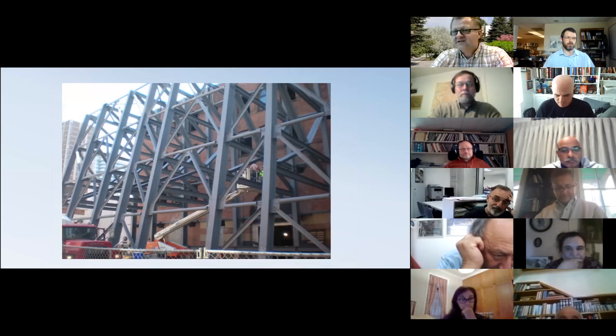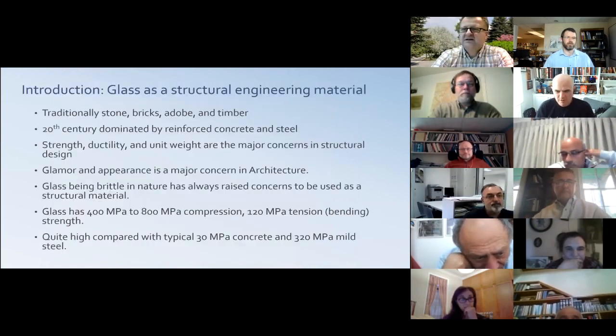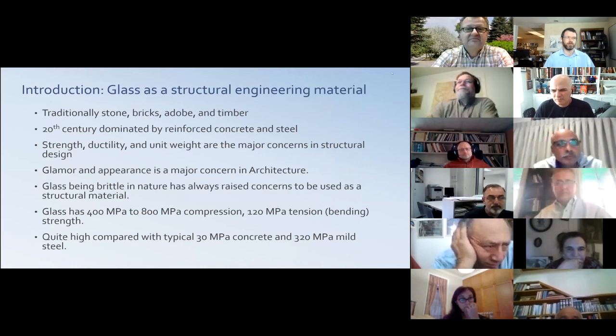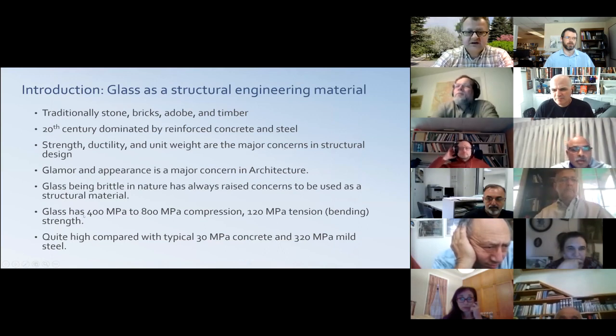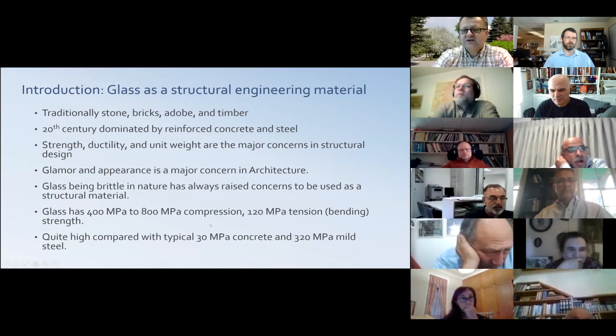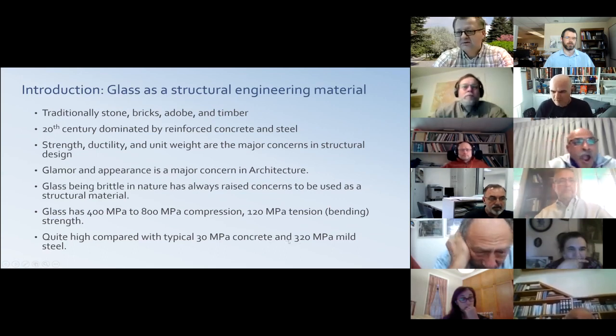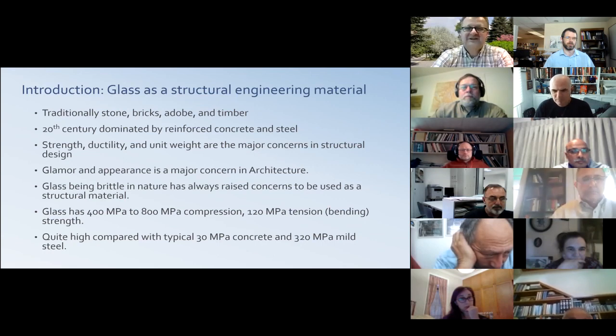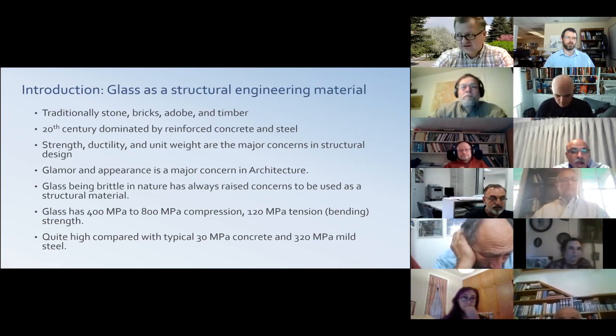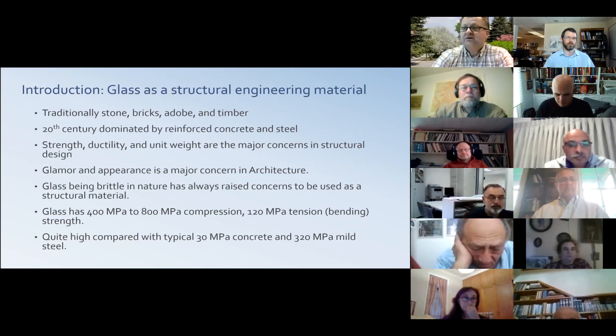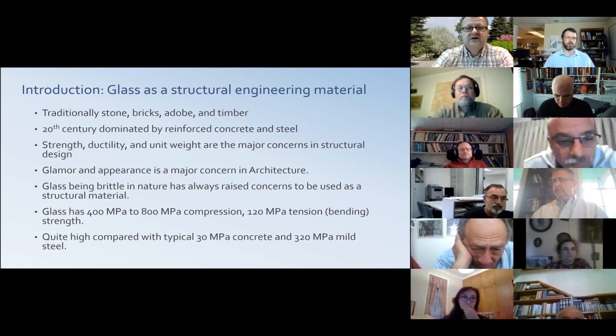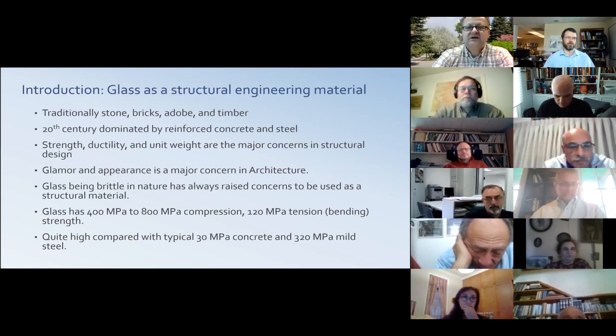You may think, how can glass be used instead of this? But it is surprising to see that glass is a very high strength material. I would just like to highlight that it is about 400 to 800 megapascal strength. So when you compare this with concrete of only 30 megapascal or steel with 320 megapascal, it's like a super material. And the tensile strength is also in the range of, for regular glass, I would say 40 megapascal, and for tempered glass, 120 megapascal. So why don't we use it for structural purposes, especially for temporary strengthening or supporting historic structures?